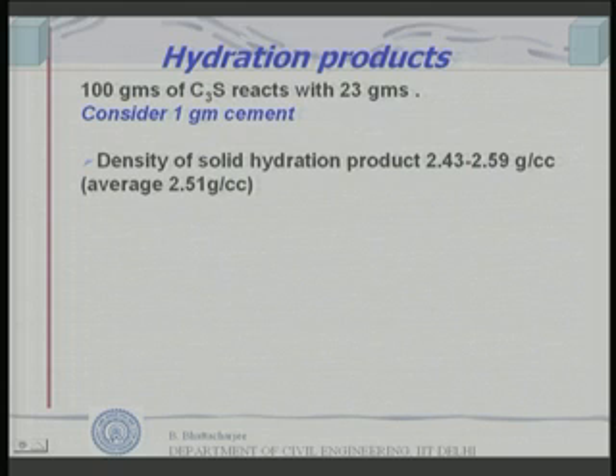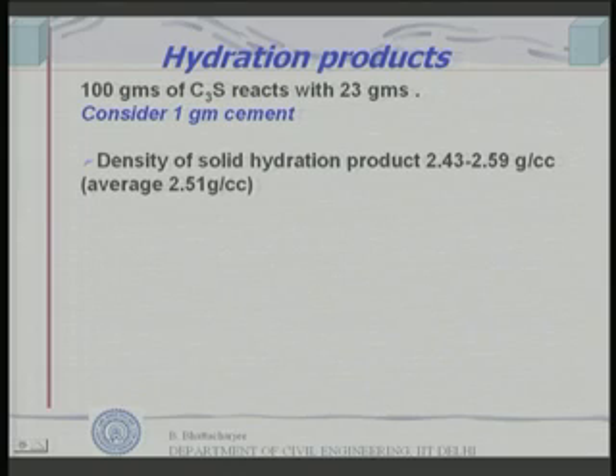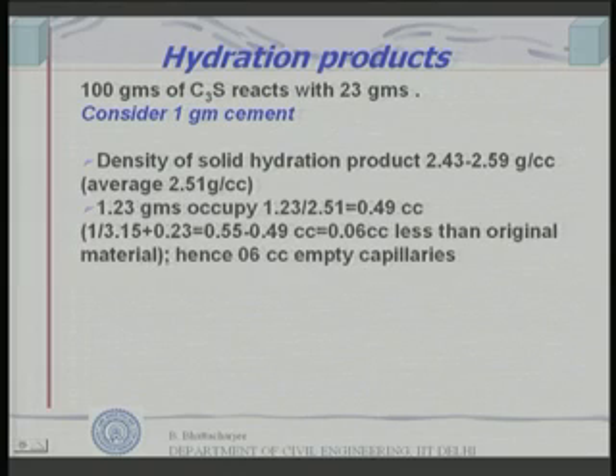You have cement, its density in CGS system would be 3.15 grams per cc, density of water 1 gram per cc. So, you have cement and water combined together in certain proportion, 100 grams of C3S reacts with 23 grams, resulting in a product which has got 2.5 grams per cc density of solid. So, 1.23 grams because 23 grams reacts with 100 grams of cement. So, if I consider 1 gram of cement, 1.23 grams of product of cement hydration would occupy 0.49 cc because 1.23 divided by 2.51 is 0.49 cc.